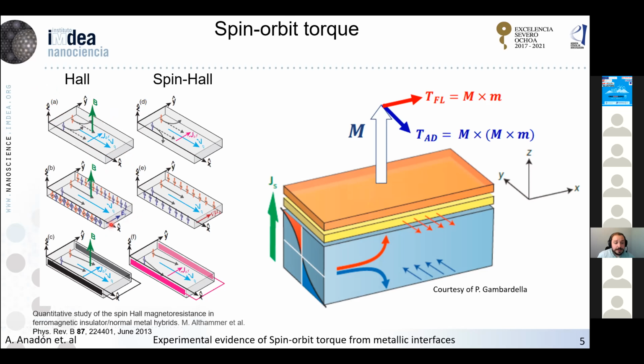in this direction. If you go to the spin Hall effect, what you have here is that when you apply an electric current into a system that has high spin orbit coupling, the scattering directions of up and down spins are different. So basically you have a spin accumulation at the edges of the sample, and this produces effective magnetic fields. And these effective magnetic fields can make modifications to the magnetization of a magnetic layer that you can put next to this layer with high spin orbit coupling. So this can be as high as to produce the switching of this magnetic layer, and this is the way you write in the spin orbit torque memories. You can also do reading by some effects like the anomalous Hall effect, for example.